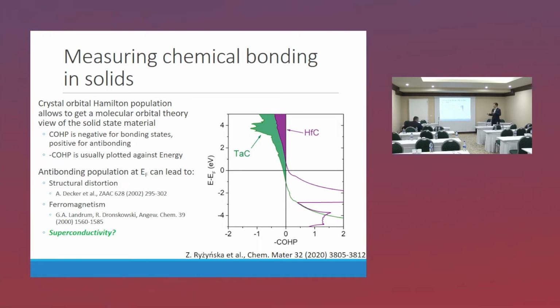And it was shown that tuning the electron count, shifting the Fermi level into antibonding states, so effectively inducing antibonding population, will lead to structural distortion. Of course, it's a great paper which describes the tellurium structure based on the Peierls distortion of a polonium structure. Okay? Ferromagnetism. So Dronskowski et al. have published a series of papers in which they were able to rationally make a material ferromagnetic by tuning the electron count only, just pushing the Fermi level into antibonding regions.